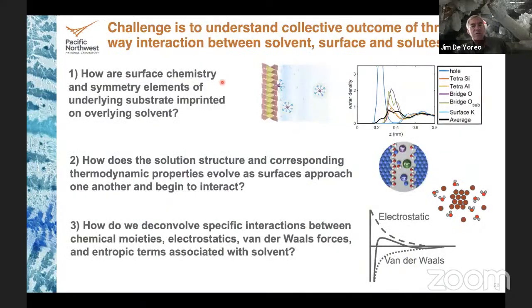So I want to end now with a set of challenges rather than conclusions. Our challenge is to understand the collective outcome of this three-way interaction between solvent, surface, and solutes. How does surface chemistry and symmetry elements of the underlying substrate imprint on the overlying solvent? How does the solution structure and corresponding thermodynamic properties evolve as surfaces approach one another and begin to interact? And how do we deconvolve specific interactions between chemical moieties, electrostatics, and van der Waals forces, and the entropic terms associated with the solvent?